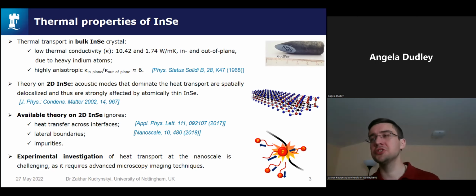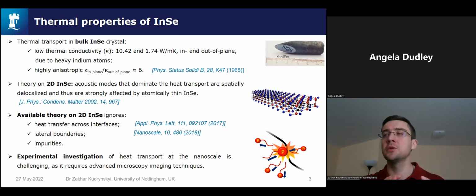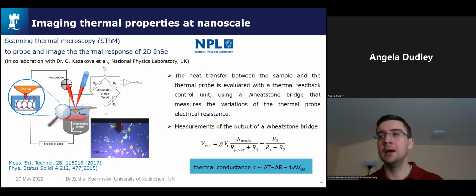An experimental investigation of heat transport at nanoscale is challenging as it requires advanced microscopy imaging techniques. To probe the thermal transport of 2D indium selenide with nanoscale resolution, we use scanning thermal microscopy. These studies were conducted in collaboration with the National Physical Laboratory here in the United Kingdom using their home-developed setup. We have a scanning probe, which is basically a microscopic object with a nanometer size radius. Our resolution is actually the radius of this probe.